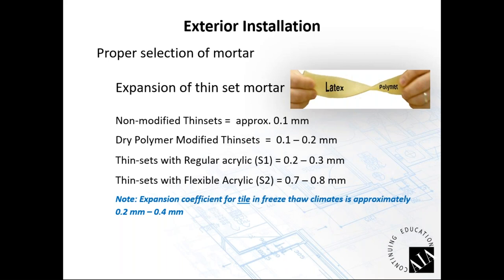Setting material companies have mortars, as many as 30, 40 mortars that will comply with ANSI 118.4. So what we have to take a look at is what do we expect to happen with this building, so that as we choose the mortar that we're going to use to adhere the tile or stone, it's going to function properly. When you look at a non-modified mortar, or a mortar that complies with ANSI 118.1, basically it's a standard cement. There's some other retardants in there that help hold moisture to it. A very simple mortar, bond your tile to a substrate. But when it's exposed to a lot of movement from heat or cold, expansion and movement, it'll break down. It'll come apart. It has very little expansion.